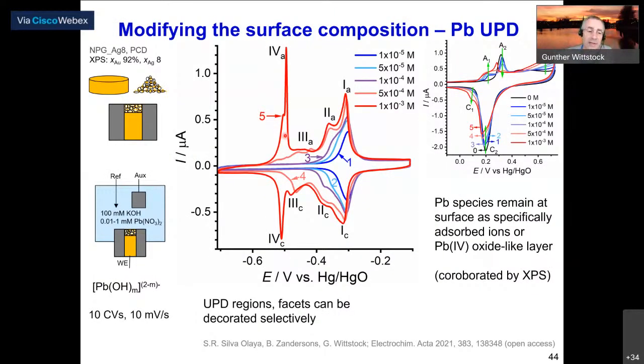We can now start to make the UPD experiments at these surfaces. And after playing around with the concentration of this lead, which we use for these UPD experiments, we can specifically and selectively decorate only certain facets of that. So if we have very low amount of lead, we can only decorate this peak. If we add more, we fill the next, energetically next favorable places. If we make more, the next one. So we can step by step fill the surface with lead species.